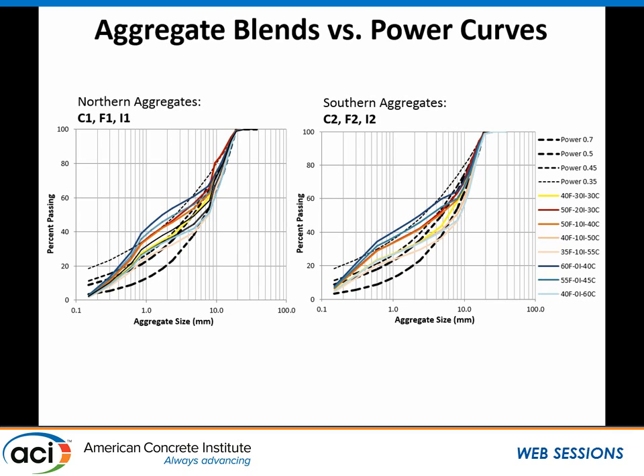Using southern aggregate and northern aggregate, for southern aggregate, 50% fine, 10% intermediate, and 40% coarse, this orange one here, is being used, which is located between 0.35 and 0.5, which is close to that best fit we showed in the previous slide. So if you take that as a practical limit, you run those packings, you can't get the highest, you still have to decide what would be your practical aggregate blend.